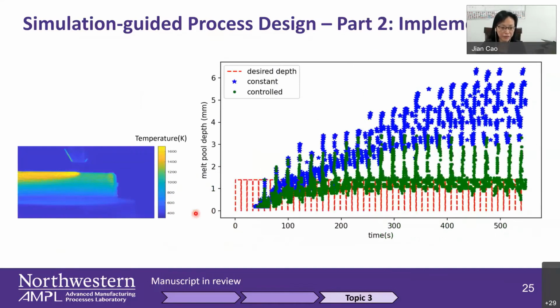So we implemented this in the experiment after you calculate it. This is not a direct measurement of melt pool depth, but from the thermal camera, from the edge, because it's a thin wall, you can kind of sense it. You can see that it's controlled pretty well.